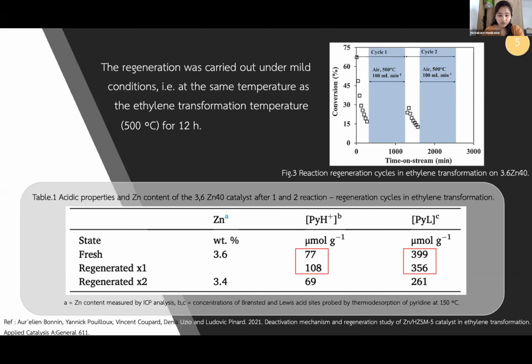The regeneration was carried out under mild conditions at 500 degrees Celsius for 12 hours. Despite the low temperature used, all coke molecules were removed but only a portion of the acidic properties was recovered after regeneration. In addition, the second regeneration step leads to a radical change in acidic properties, mainly for Lewis acid sites, and loss of zinc content.